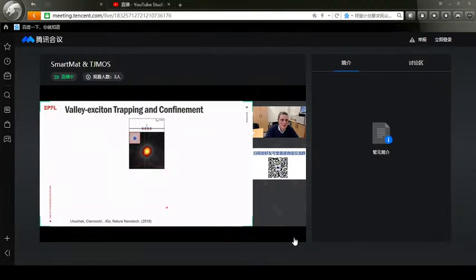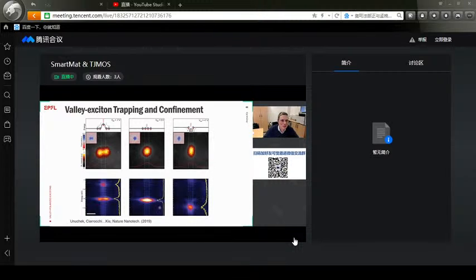Now, the other thing that is interesting here is that we can use this potential arrangement to also trap and try to squeeze excitons in one place. So using this arrangement of electrodes and voltages, we can either push them out of a region, or we can confine them into a region. And then when we confine them, by looking at the energy difference between the free excitons and the confined excitons, we can actually estimate the density of excitons in this structure.